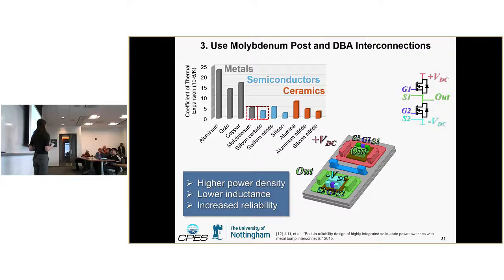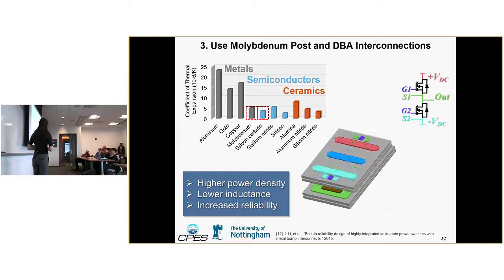So with this, by eliminating wire bonds, you can increase your power density, reduce your parasitic inductance, and also increase the reliability, because wire bonds are not known for being reliable. They break and lift off very easily. And then we use a top insulating ceramic substrate to finish that interconnection. That connects the source of the high side switch to the drain of the low side switch. So the green here will connect to the green here through this upper connection. And there are vias in these ceramic substrates to bring all the electrical connections to the top.